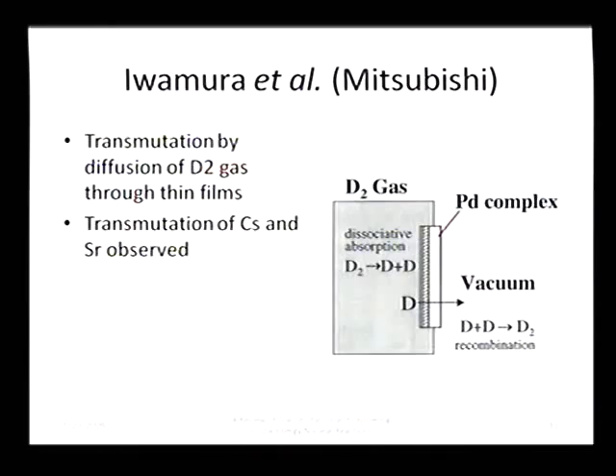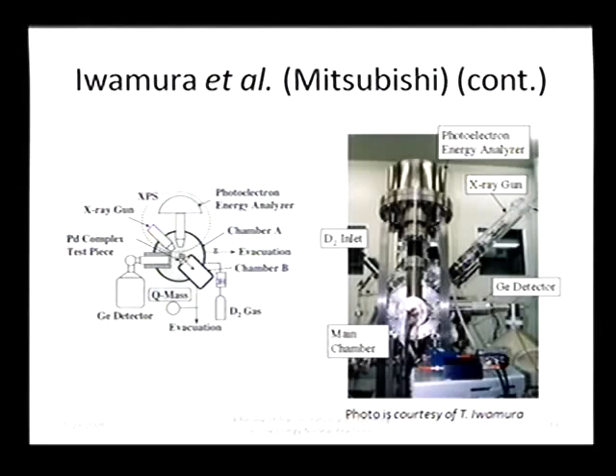Other groups that I thought might be worth reviewing, because I think some of this work again supports these observations. There's transmutation by diffusion of deuterium gas through thin films by Iwamura. In essence, this was a very simple experiment where deuterium gas was pressurized on one side of a structure made of a palladium complex, and transmutations were observed in the cesium and strontium. The experimental system is shown here, and again, it had a number of very interesting diagnostics associated with it.